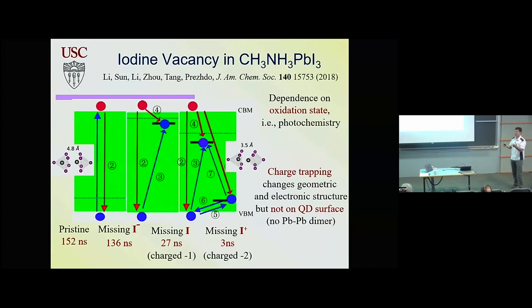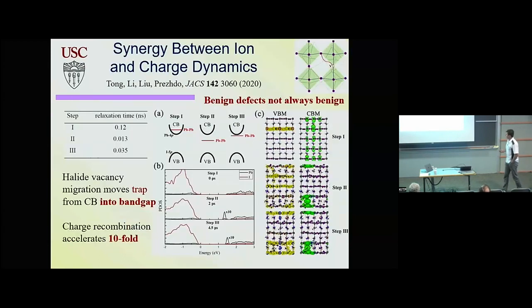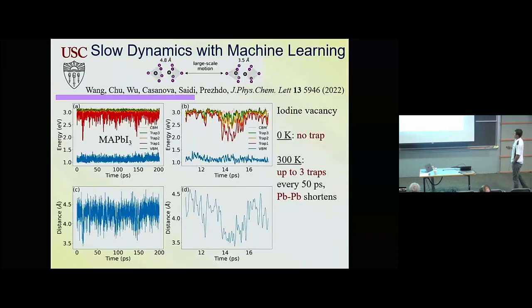Again, something that's not going to happen in lead selenide or cadmium sulfide, because they're much more rigid. Here you have a soft material that can create new chemical species inside. So you have photochemistry basically in this material. This can also happen when defects diffuse. A vacancy creates no mid-gap state, but then the vacancy diffuses to a new location, and when it's diffusing, the mid-gap state shows up, and this influences lifetime. The same thing can happen without charge, without diffusion, just simple fluctuation, but on a very slow time scale.